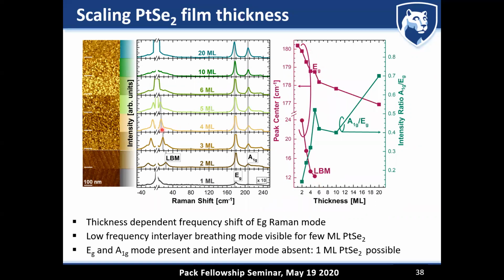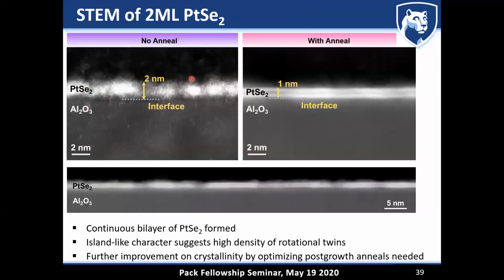Now, looking at all of those, you can see that there's some sort of formation of platelets here. Interestingly enough, here for these two monolayer platinum diselenide and sapphire, the whole AFM, atomic force microscopy, morphology still looks like what we used to see on sapphire. And so we took those films and took a cross-sectional image using scanning transmission electron microscopy.